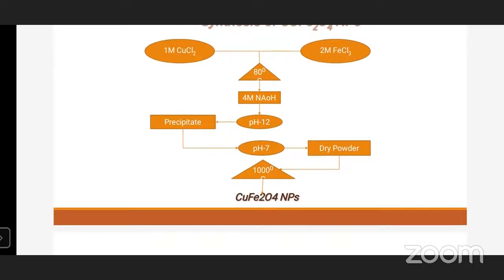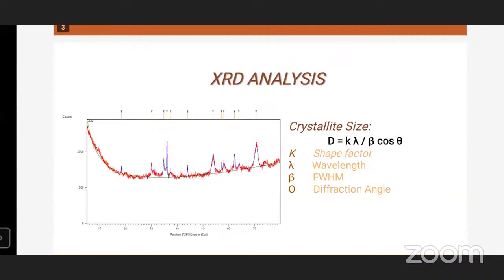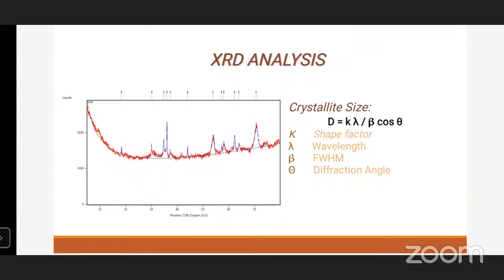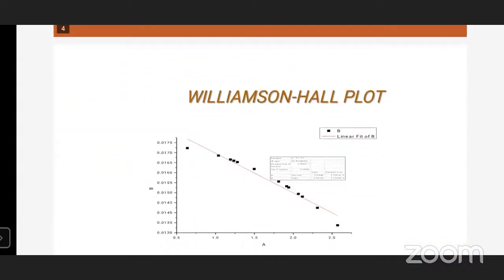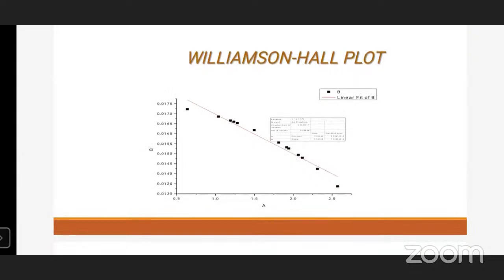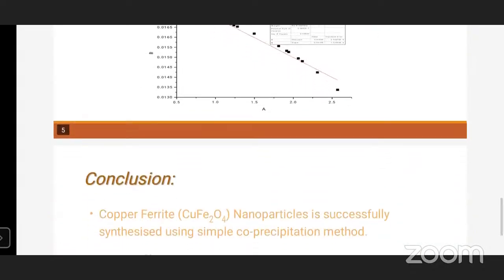To characterize the fine particles, I have used X-ray analysis. From the XRD analysis, it is clear that the observed particle is copper ferrite, as it has peaks at 34 to 36, and the crystallite size is calculated using the formula D equals K lambda divided by beta cos theta, where K is the shape factor, approximately 0.9, lambda is the wavelength of the instrument used, 1.5406 Angstrom, beta is the full width at half maximum, and theta is the angle of diffraction. Also, the Williamson-Hall plot method is used to analyze the crystallite size of the sample.